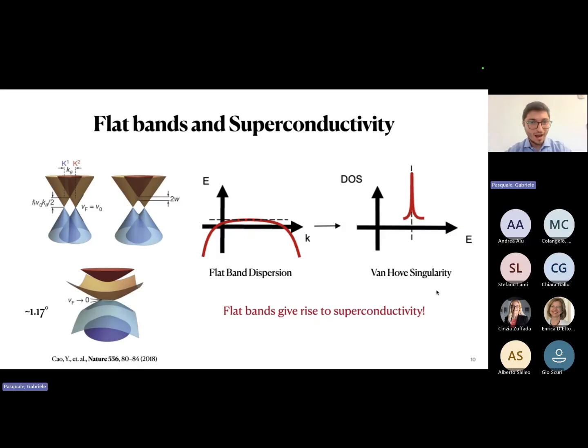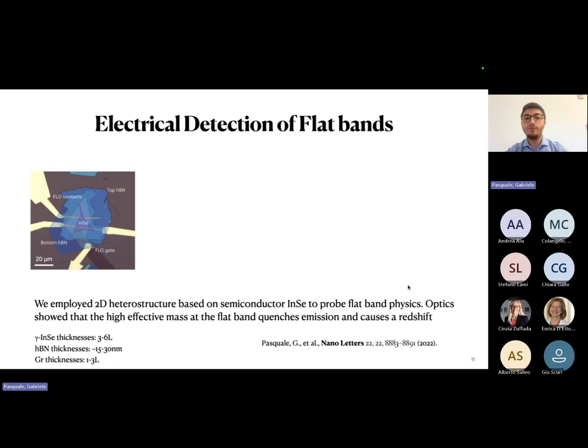So far, so good. However, there is a problem, which is that these flat bands are extremely hard to detect experimentally. Usually, it's something that you detect after many months of measurements, and you realize that you have a phase transition. So the question that I want to ask is: is there a way to detect experimentally, in a quick and reliable way, where these flat bands are in the energy diagram, and then use them for discoveries?